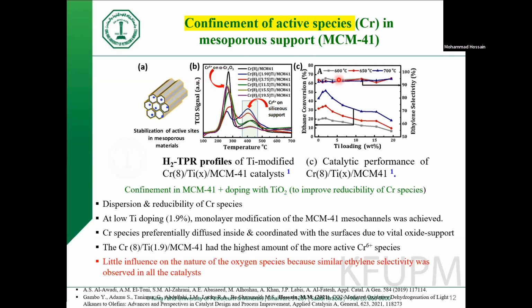Now, in terms of product selectivity, all these catalysts with different titanium, but constant chromium loading, give the same ethylene selectivity. That means titanium plays a role in bringing the available lattice oxygen, and a small amount of titanium is doing a good job compared to a higher amount. And of course, the selective sites remain unaffected by the variation of titanium.